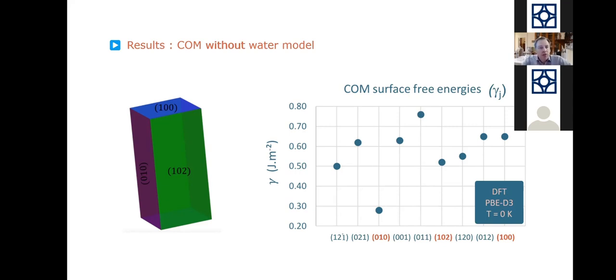and we can compare our proposed morphologies with the experiment. So let's first start with the simple monohydrated case, and let's say that we do the same. We calculate the surface energies here along all these different orientations that we've chosen. Yes, these are the different orientations. See this is the x-axis. Yes, so we do this with DFT. Yeah, so PBE functional, D3 correction. If you have some questions, you can always ask me in the chat. And then we plot here our surface energy calculated with the formula that I've shown you. So here are the dots corresponding to these values on the several surfaces.